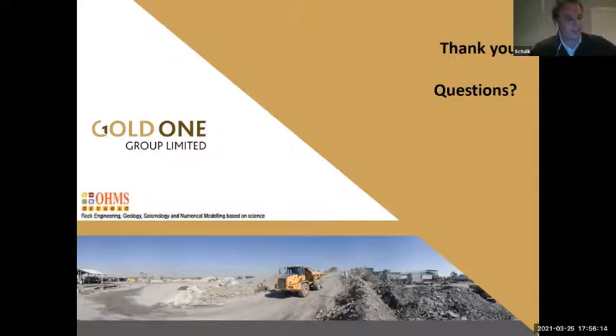Yes. What we did is that we got our own core driller. It's a Hilti drill with a 74 millimeter barrel, which we use to drill cores from the packs. What we found is that you normally get this microfracturing, or we suspect it is microfracturing, in the first about 5 to 10 centimeters of the skin of the pack, because that part of the concrete normally breaks off when you retrieve the core. But that can also be because when you pump the bag under pressure, all your fines, which is normally your cement, get pushed to the outer corners of the structure, and there might be a cold joint there as well. But we suspect that might be microfracturing.